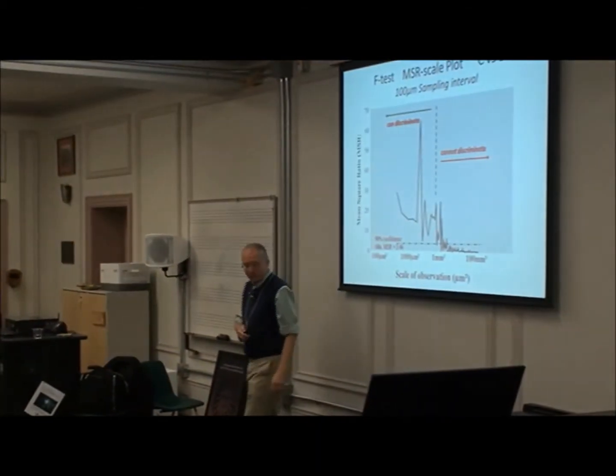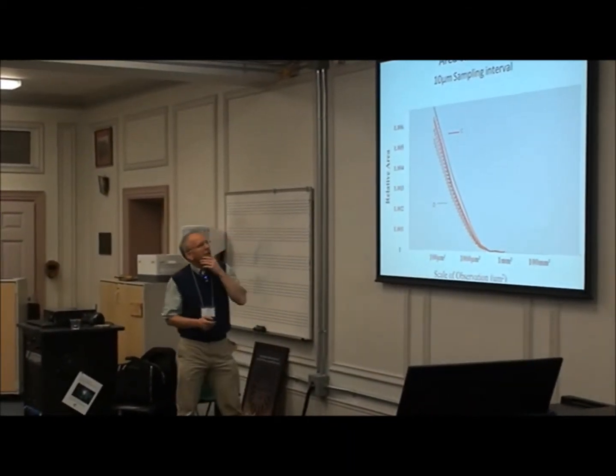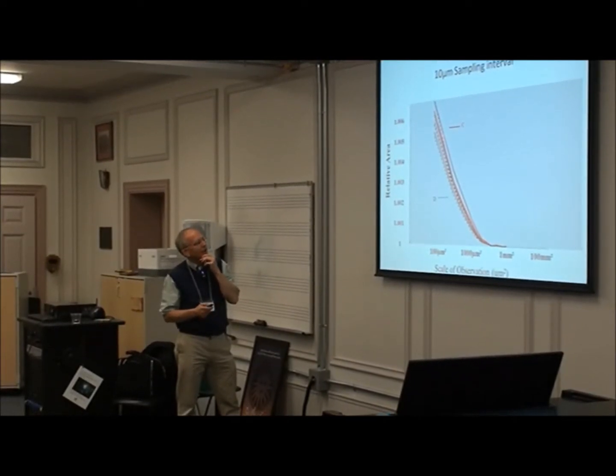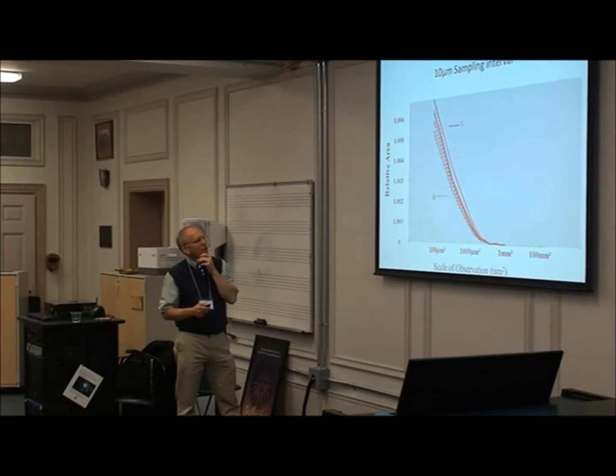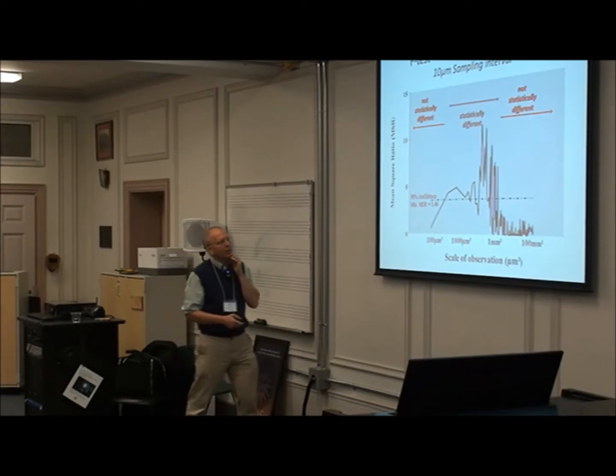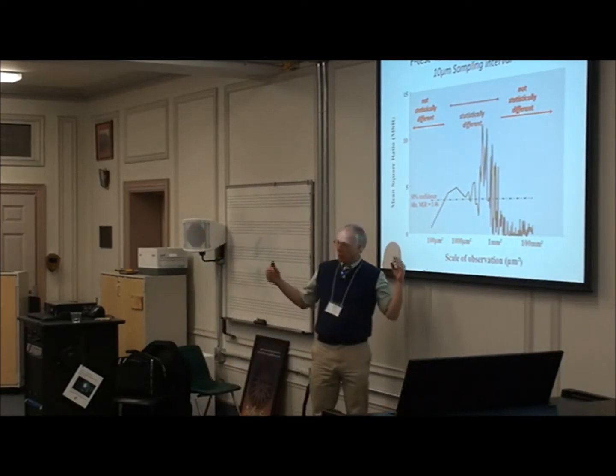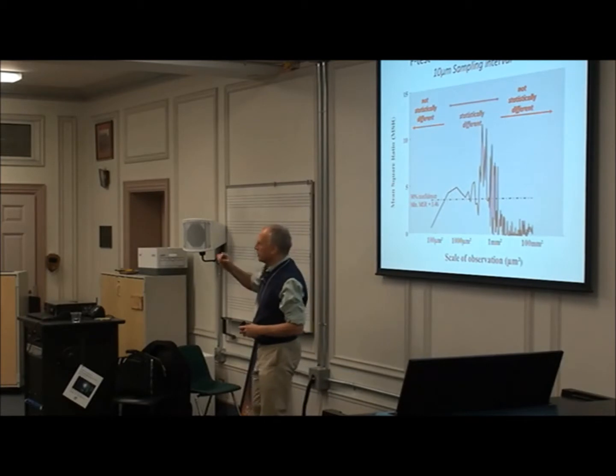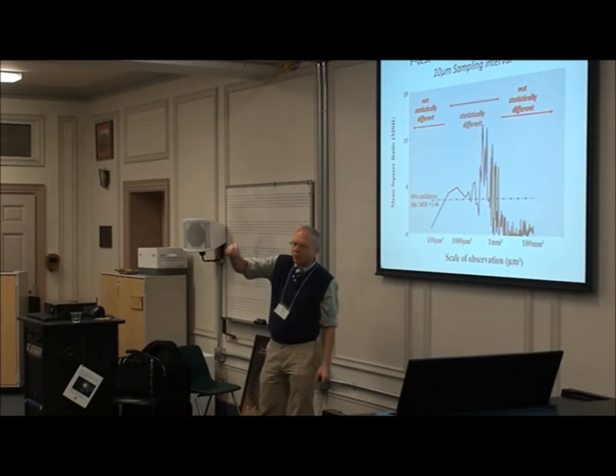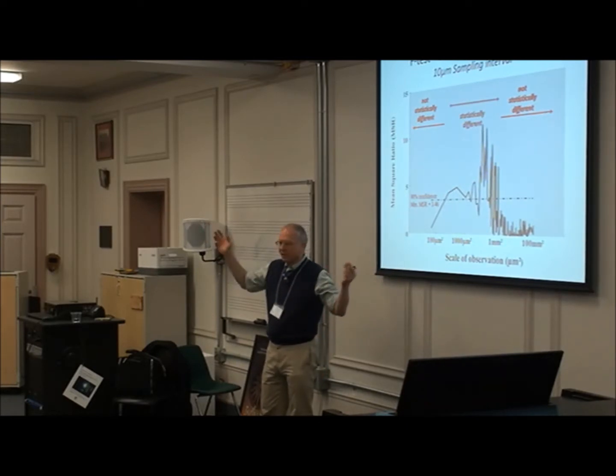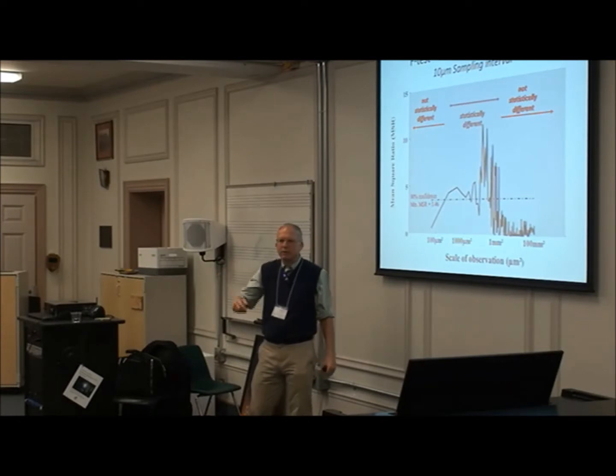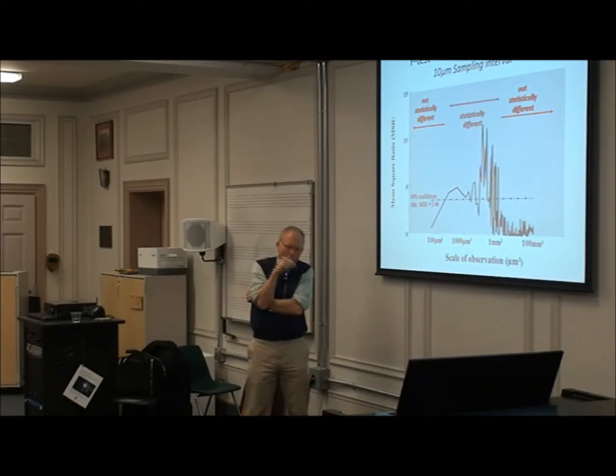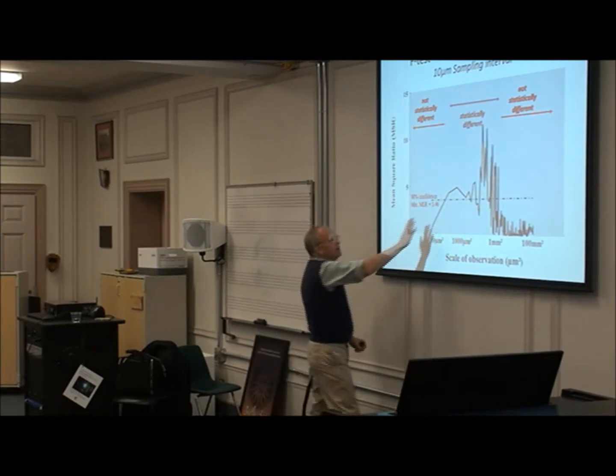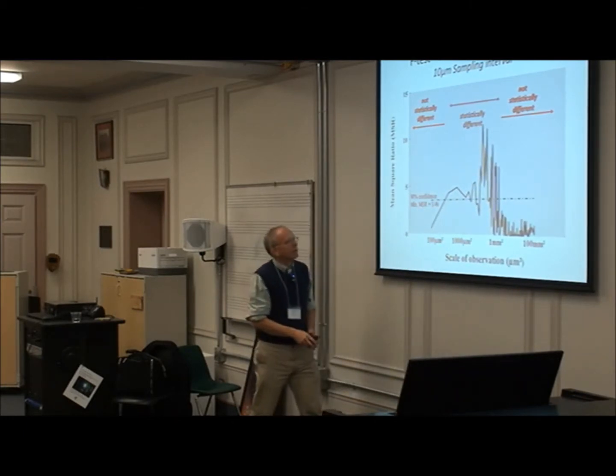Now, we could ask, what about something else? Does anything else work? Let's take a look at a finer scale too. So here's the 10 micrometer sampling interval. It doesn't look so good. Some of that might be because of the problem we had with the measurement. And some of it might be because when we zoom way in, we're seeing what happens when one grit gets dragged across the polyethylene, and it doesn't see what the rest of the dressing looked like. It's just that one grit that's moving there. So if I zoom in at some level, I'm seeing one grit-polyethylene interaction, and that might be what's out here, or it could be my measurement noise.